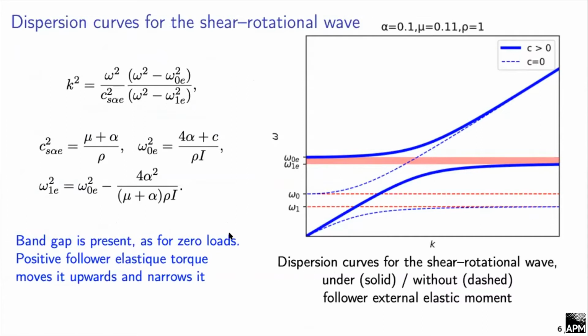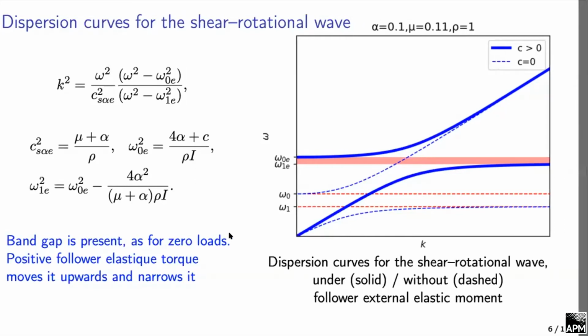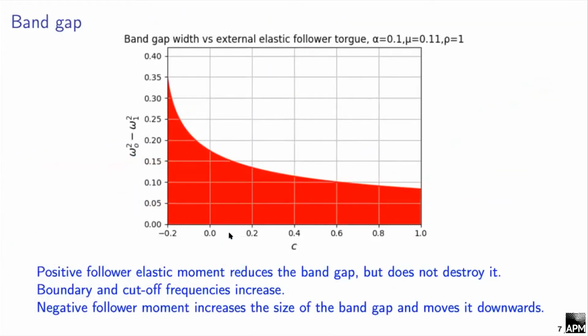We can see that there will be a band gap, so it's obvious, but comparing these results with a dispersion curve for a reduced isotropic Cosserat medium without the influence of the external torque, we see that the elastic following moment in our case reduces the band gap and increases the value of the boundary frequency and the cutoff frequency. So what does it mean? It means that the positive following elastic moment reduces the band gap, but it doesn't destroy it. However, using a negative tracking moment that does not lead to instability, we will get the opposite effect.